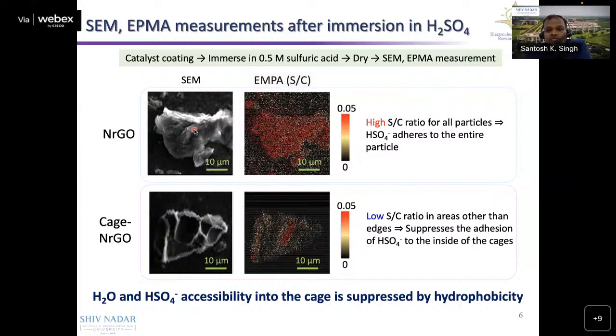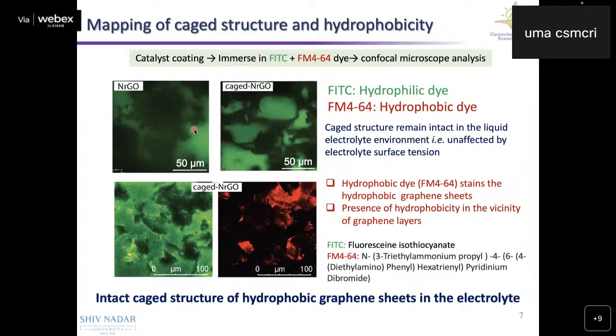Further, we tried to confirm the role of hydrophobicity, and whether the morphology of this kind of porous catalyst remains intact in solution or not. So we did confocal microscopy analysis using different kinds of dye: the hydrophilic FITC dye and the hydrophobic FM464 dye. Here we can see that NRGO, the hydrophilic one, is completely submerged in the hydrophilic environment of the hydrophilic dye. However, the caged NRGO shows that the caged structure remains intact under solution conditions as well.